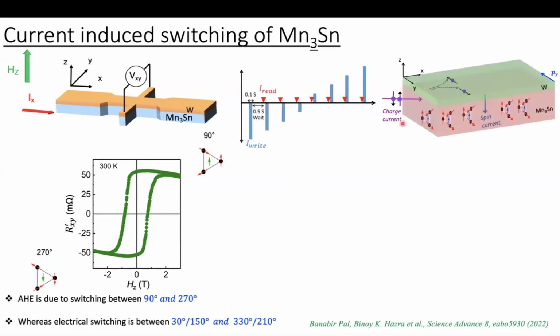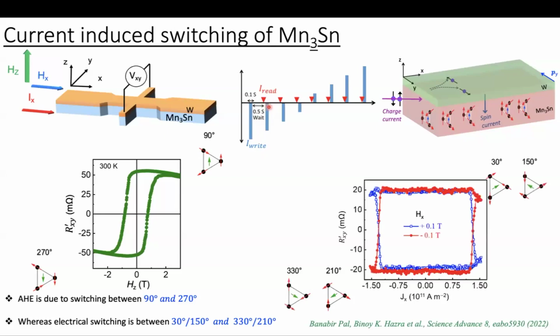Then we performed the current-induced switching experiment. In this experiment, the charge current is passed through this bilayer, and the tungsten layer generates spin current due to the spin-Hall effect, and that spin current propagates to the proximal layer, here manganese-3 tin, and applies a torque on the net moment of the manganese-3 tin. Here we use two protocols, and in this presentation I will discuss only one. In this protocol, we apply a 100 millisecond writing pulse and then wait for a few seconds, like 0.5 second, and then we apply a small read current, 1 milliampere, and measure the Hall resistance. What we observe is a deterministic switching in the presence of a bias field. The bias field is Hx, which is along the x direction.